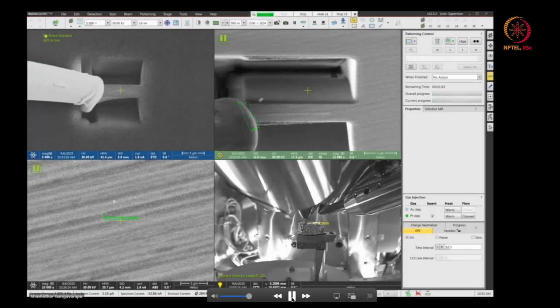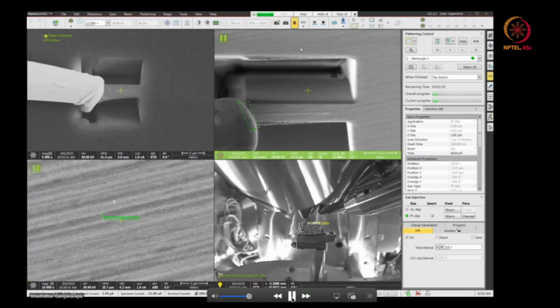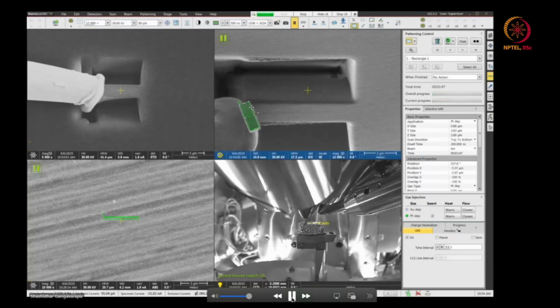So now the platinum deposition is going on. Now it's making a bond between this micro manipulator and our sample. So you have to take a snapshot in between to check how the bonding is happening. Is it bonding or welding or not? Yeah, it's bonding actually. The welding, the deposition is going. Yeah, it's nicely deposited. You can see. So once this deposition is done, then we will cut from the left side. Then we can easily remove our lamella from the sample.